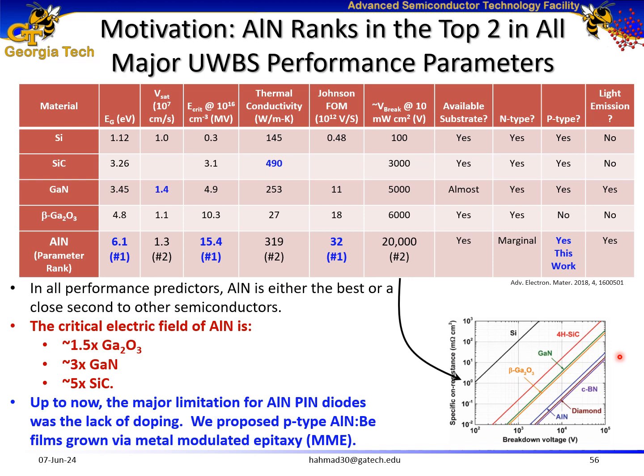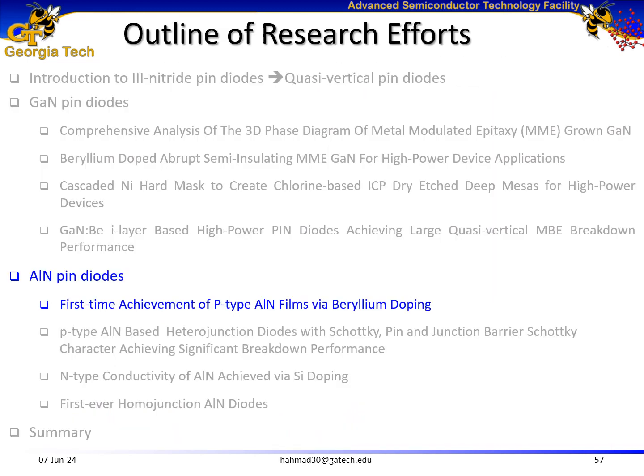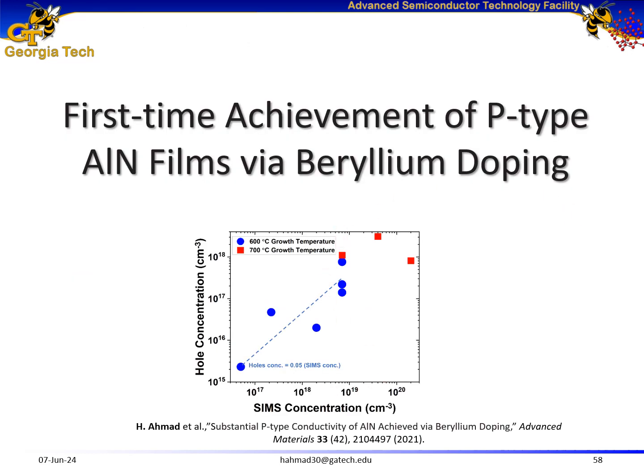My major motivation for this study is that aluminum nitride ranks in the top 2 materials in terms of ultrawide bandgap semiconductor performance parameters. For example, the critical electric field of aluminum nitride is 1.5 times that of gallium oxide, 3 times that of gallium nitride, and approximately 5 times that of silicon carbide. But up to now, the major limitation was p-type doping, the lack of doping in aluminum nitride. And we first proposed the beryllium-doped aluminum nitride p-type films grown via metal modulated epitaxy. So I performed a study on first-time achievement of p-type aluminum nitride films via beryllium doping.